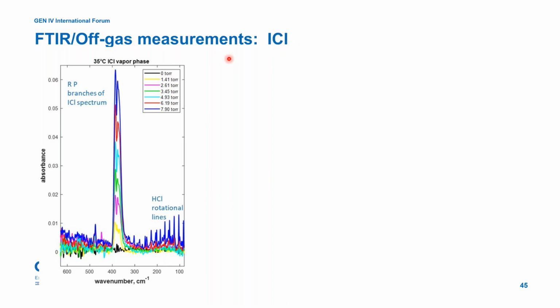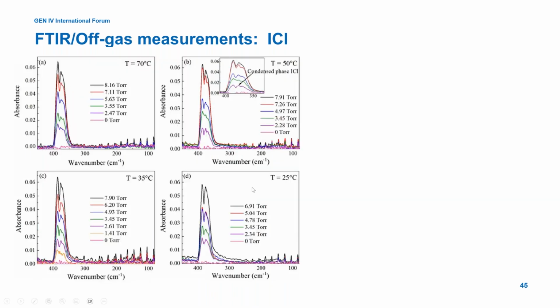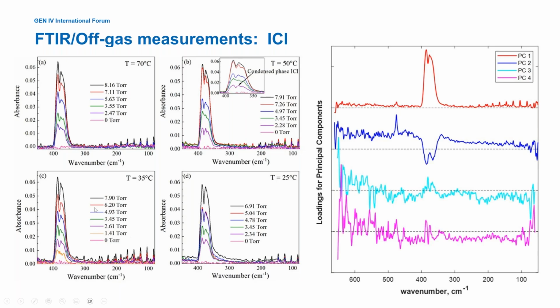In this case, ICL is actually infrared active. So we use a far IR technique using an FTIR system. We measure the ICL bands as a function of pressure. We measure this not just as a function of pressure, but at variable temperatures from 25 up to 70 degrees in the gas phase. And we're measuring it at pressures up to about 10 torr.